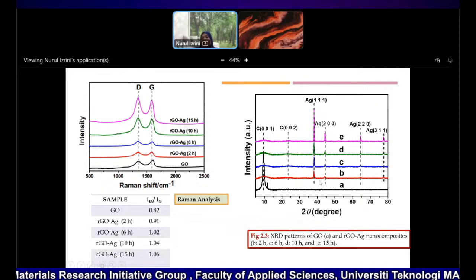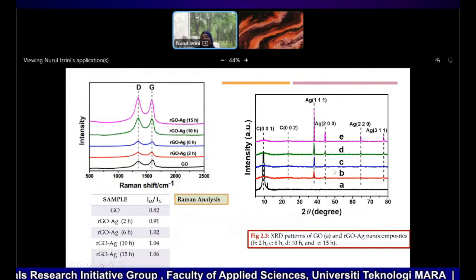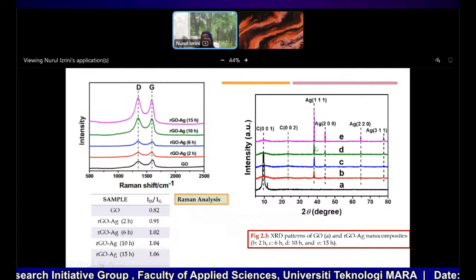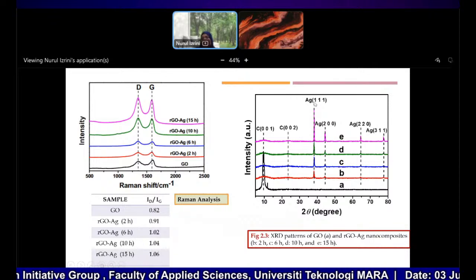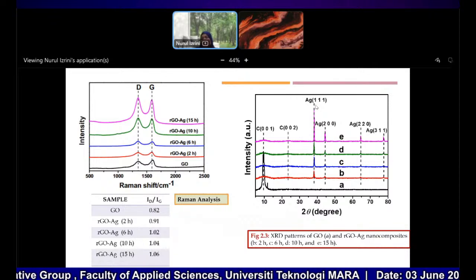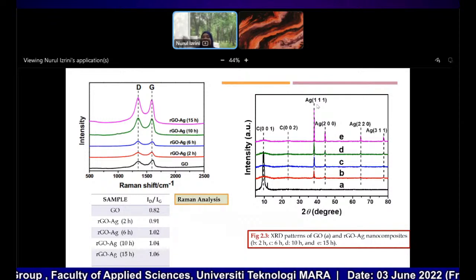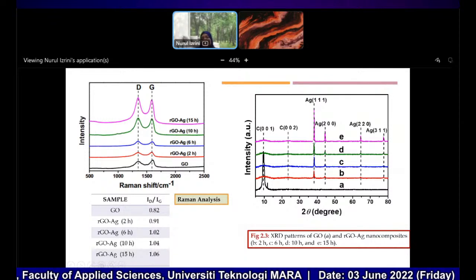We also did XRD to make comparisons between all reaction times. For the 15 hours sample, we can see the crystalline Ag at the HKL sides, very sharp peaks and very high peaks.